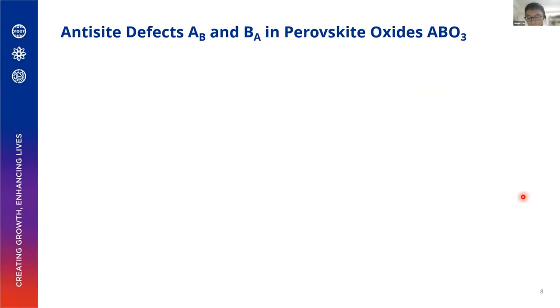Okay, now let's go to our material system. Before that, let me introduce one kind of defect in perovskite oxides. It's called an anti-site defect. Basically, in the ABO3 perovskite structure, you can have the case where the A-site atoms sit on the B-site position, or B-site atoms sit on the A-site position, depending on the stoichiometry.